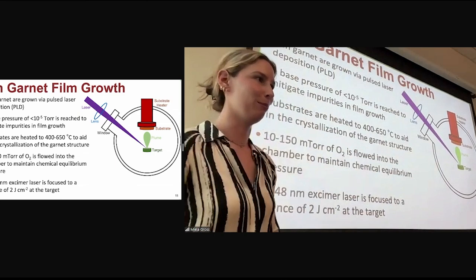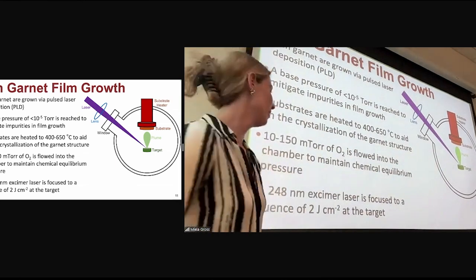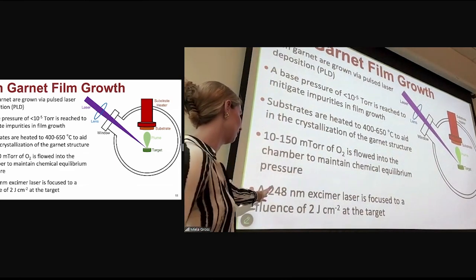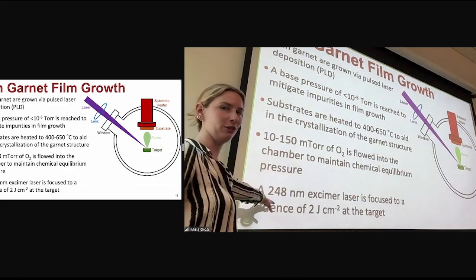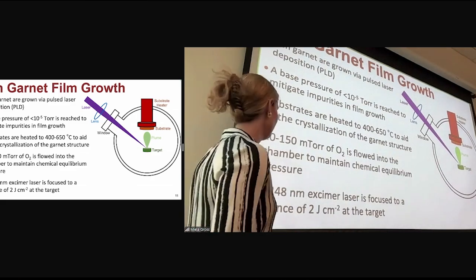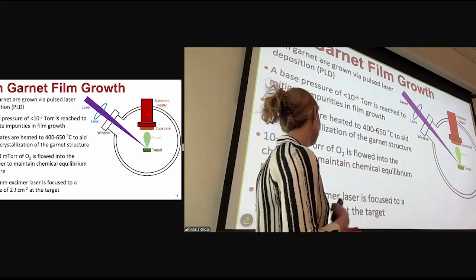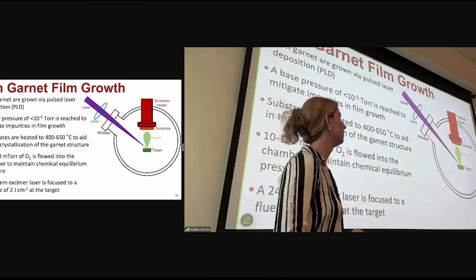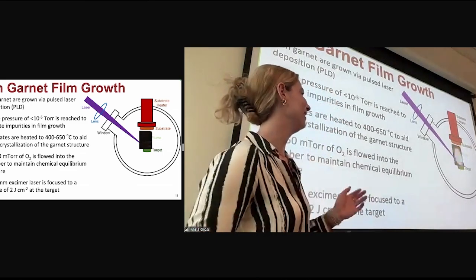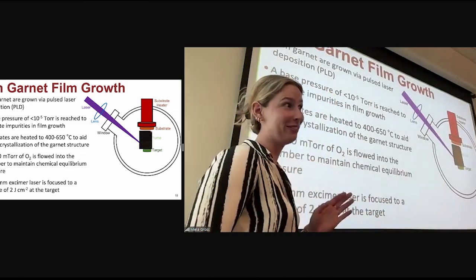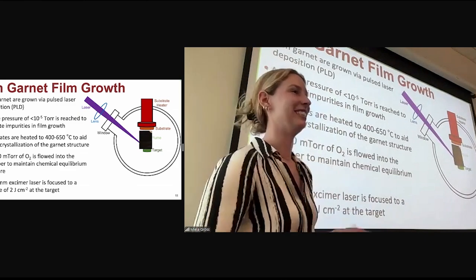Lastly, it wouldn't be called pulsed laser deposition without a laser. So we use a krypton fluoride excimer laser, which has a wavelength of 248 nanometers. And it's focused to a fluence of 2 joules per centimeter squared at the target surface. And I added a little video of garnet growth live to show you all what this process looks like.